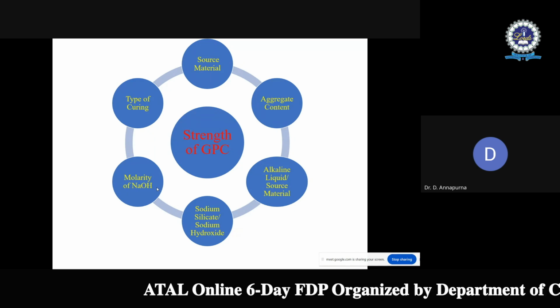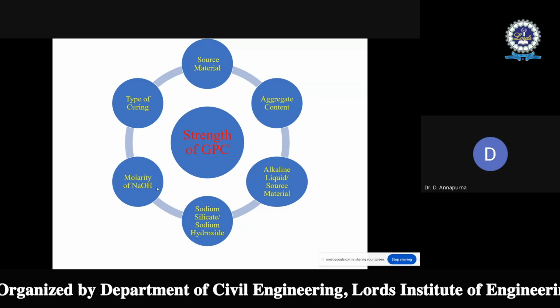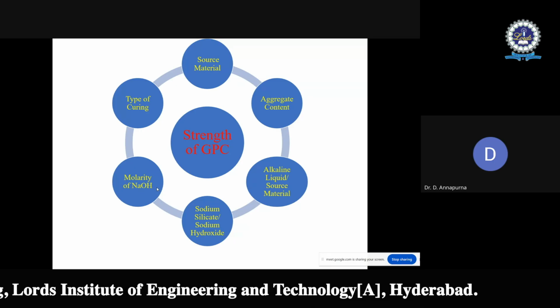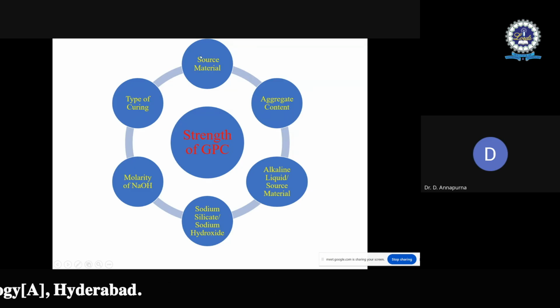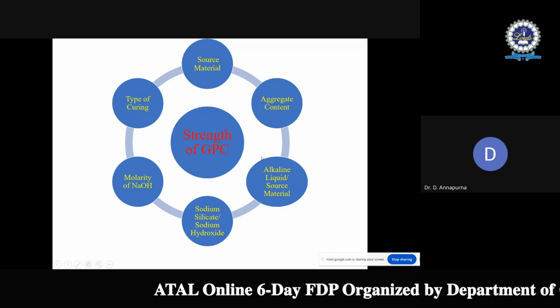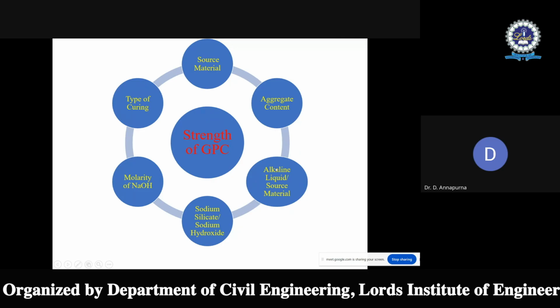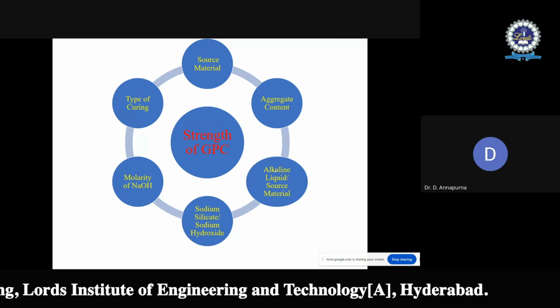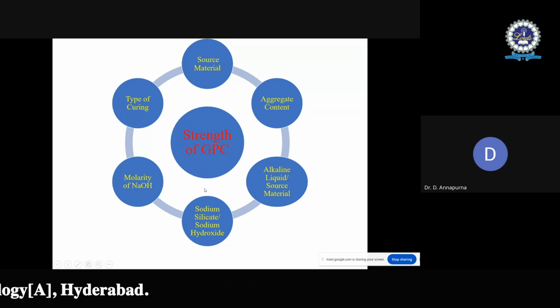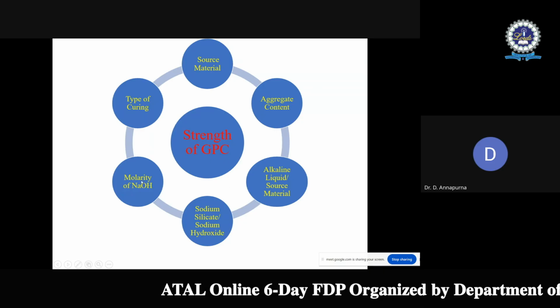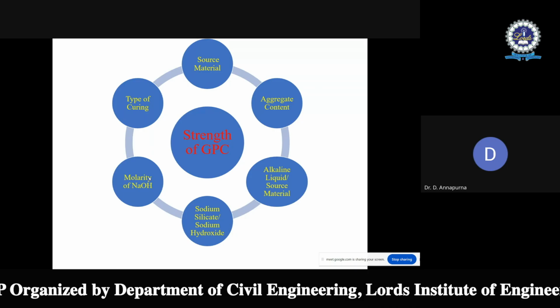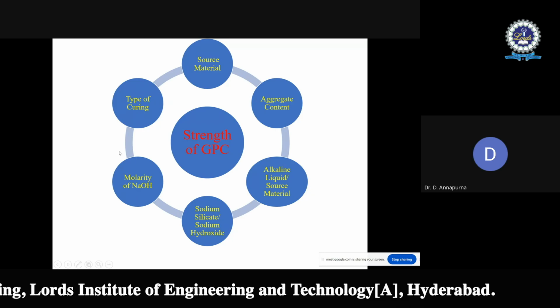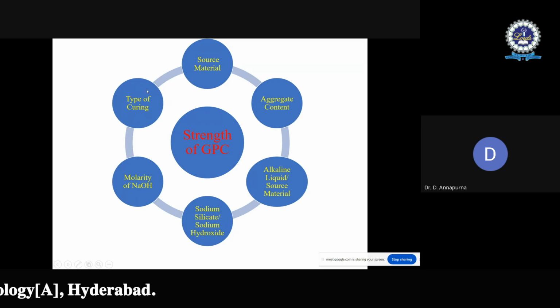When the literature was searched to see what different parameters influence the strength of geopolymer concrete, it was identified that the source material is going to influence the strength. Then the aggregate content: if it varies, the strength of geopolymer concrete is going to differ. Then the alkaline liquid to source material ratio also influences the strength. Then the type of alkaline activator, that is sodium silicate and sodium hydroxide, and the ratio between them also influences the strength. Then the molarity, because the concentration of sodium hydroxide plays a very important role in geopolymer concrete, so the molarity is important. Then the type of curing; I said heat curing was used by different researchers.